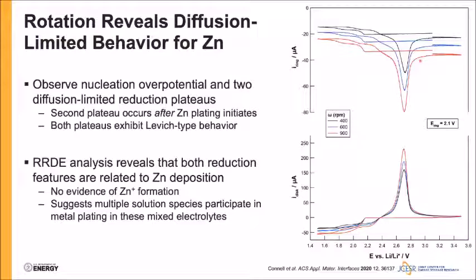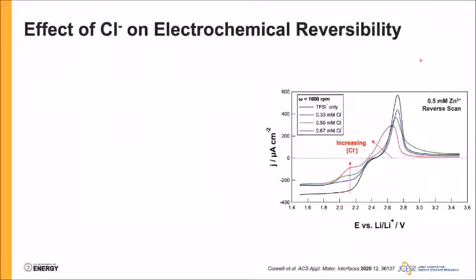And so to understand what's driving this behavior, we can start playing around with the solution composition. What I'm showing here in this scan is focusing only on the reverse scan, where deposition ceases, more or less corresponding to the thermodynamic potential for metal deposition. As we play around with the chloride concentration, we see two very interesting things happening. The first is that as we increase the chloride concentration, the magnitude of the current density associated with this first reduction plateau decreases, suggesting that in order to access the full current density accessible in the system, you have to go to higher and higher overpotentials, more and more negative potentials.